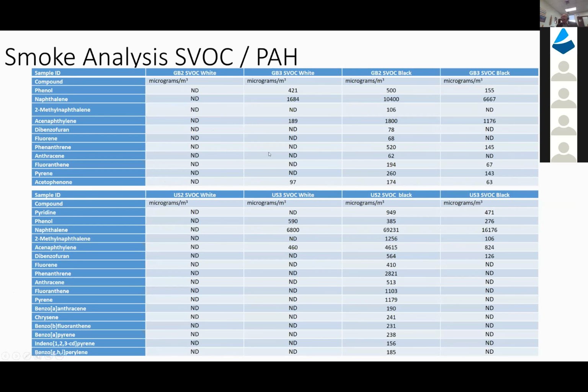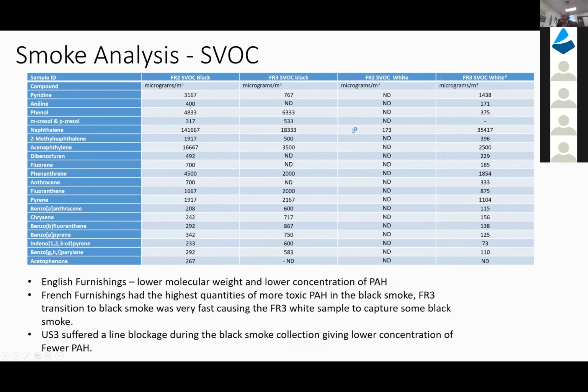And we see that same sort of thing with SVOCs. I've primarily listed here the PAHs, the polyaromatic hydrocarbons. Those are the chemicals of concern in smoke that will cause cancer. The larger molecules like phenanthrene, anthracene, fluoranthrene, pyrene, and benzopyrenes especially are the ones that cause the biggest problem. You see very, very little of that pre-flashover for 20 minutes inside of a GB UK room. But as you get past flashover, you start to see more of it, but they're nowhere near the numbers that you see for the US room. And on the next slide, we have, sorry, skip one, the French rooms. You can see those numbers are quite high.